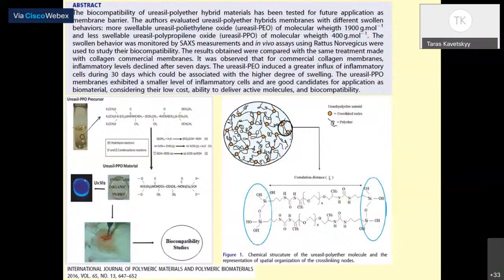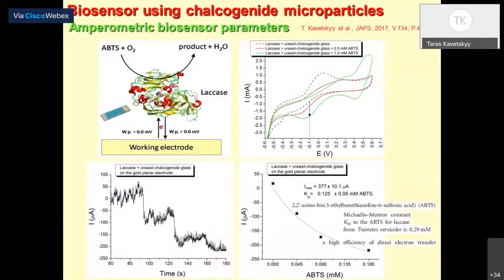And we also feel that the changes in crystalline density and free volume may affect the biosensor's characteristics. Next slide. So here we constructed these biosensors using the ureasil-chalcogenide glass matrix, and what we found, we have very good results. For instance, when we see the Michaelis-Menten constant, which reflects the efficiency of direct electron transfer from enzyme to electrode, we found that the value is 0.125 millimole for ABTS. It is even lower than for natural laccase from Trametes versicolor, 0.29 millimole. It means that we have high efficiency of direct electron transfer in this biosensor using the ureasil-chalcogenide glass matrix. Next slide.